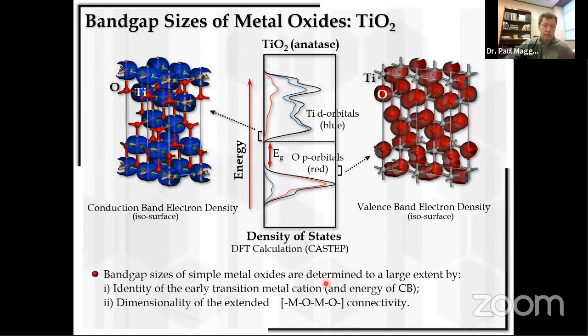Okay, so what's important? The identity of the early transition metal cation is important. It determines the energy of the conduction band. But then as well, the dimensionality of that crystalline oxide network is also important. You're only going to have a high mobility in the directions of high conductivity or extended conductivity of that network.